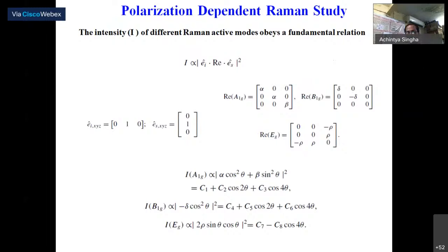So from this Raman tensor, if you know the Raman tensor of the system, then you can calculate the intensity of the modes. Now you can perform this polarization dependent Raman measurement and match it with the intensity profile that you have calculated. From there you can verify the symmetry of the system.